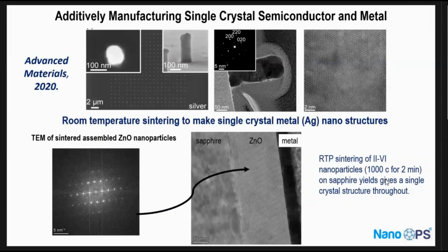Another development that we had, which was just published a year ago, was a directed assembly technique using silver nanoparticles. In this case, basically on the top here, all the pillars were single crystal. And this was also done in about a couple of minutes over a wafer level. The interesting thing is that if the particles are small enough, meaning 10 nanometers or smaller for metal, and 20 nanometers or smaller for dielectric or semiconductor, they fuse on their own. If they are larger, in many cases you can't get small enough, so you have to use sintering temperature.